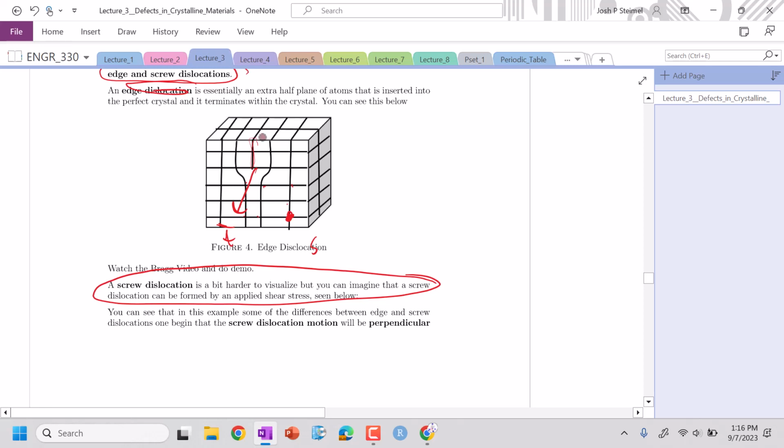So if my starting point and my finishing point are the exact same, then there's no defect involved in there. The Burgers vector is zero. So I need to make sure to draw the circuit large enough to encapsulate my defect.